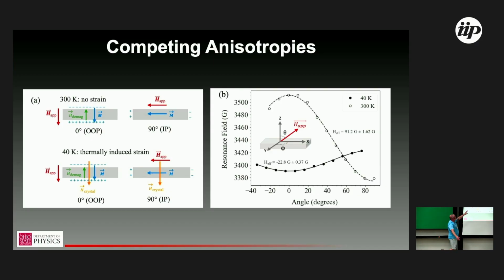So you effectively just get rid of that additional offset field, right? So the only explanation for what we're seeing is that as you cool things down and the crystal distorts and strains, you're introducing an additional crystal field anisotropy that's oriented in the same uniaxial direction as the thin film. And so that's present and pointed in the same direction, whether your magnetization is in plane or out of plane.